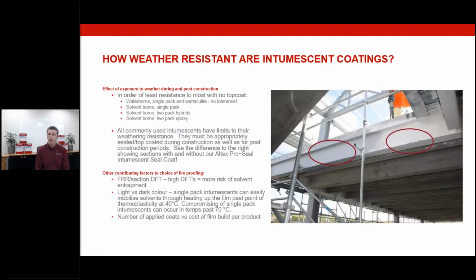The items on the left-hand side that had been sealed up properly, no effect on the actual coating itself, no compromise of the actual coating physically, as well as we took samples from it and tested here in our lab in Tauranga just to make sure that it still had the activation qualities within it, and confirmed that it did. So it had done its job. That particular coating had been developed because of the knowledge that single pack solvent-borne coatings have a limitation of weathering. So that's enabled us to be a lot more secure within our recommendations of whether that system will be lasting during the construction period.